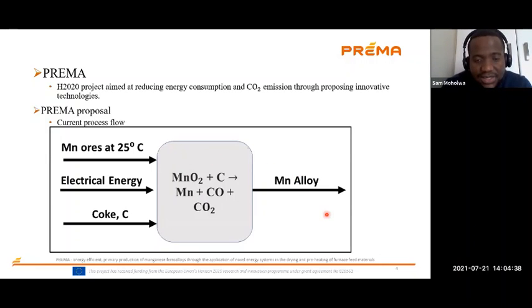This process sheet here is the current process that we use to produce manganese ores, manganese alloy. We have manganese being fed into the SAF with coke and some fluxes. Then we add electrical energy to melt this stuff. Then we get the product which will be Mn alloy, some gases and the slag. Then PREMA proposed adding a preheater to this current process of producing manganese.